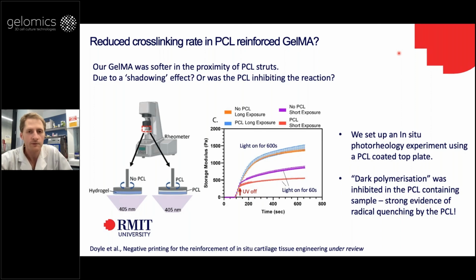So, one more example on this, we had a study where we were also reinforcing GELMA using polycaprolactone, a bit like what Ferry was talking about before. And we were finding that the GELMA was softer than we would expect in the vicinity of the polycaprolactone material. And we knew from the direction of the light that it wasn't a shadowing effect. It wasn't like the PCL was blocking the light, and that was causing the softness.